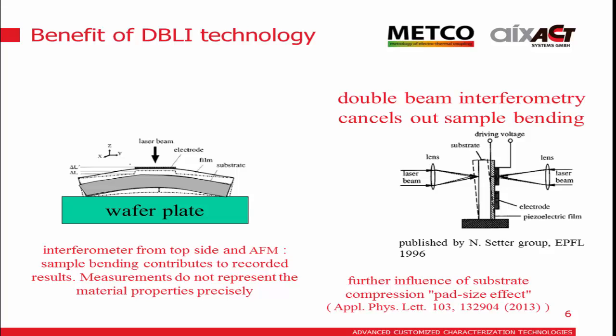That is where the double beam laser interferometric method was developed, to be able to measure the precise strain of the film itself, which is in the range of a few nanometers or even picometers. There are also further influences of the substrate, which I won't focus on here, but that, for example, create a pad size effect because the substrate is compressed and so on. These are further challenges that are part of other work as well.